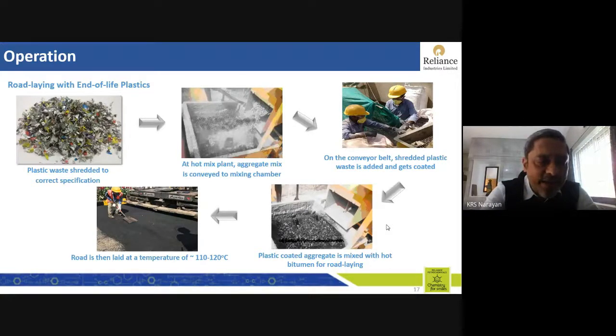So when the size of the aggregates is around 10 to 15 millimeters for the top 30 mm seal coat, top 30 mm bituminous coat, you will need plastic waste shredded material of less than 5 mm size, such that it is able to coat at the temperatures which are warranted at the drum mix plant. So when the aggregate is conveyed through the conveyor, the plastic is also dispensed through it, and then it gets coated during the melting process. And once it is coated, then you add the bitumen. After a few minutes, the bitumen is added through the bitumen dispenser to the plastic coated aggregate, and then the final mix is transported to the site and laid at 110 to 120 degrees Celsius with a 10-ton roller.